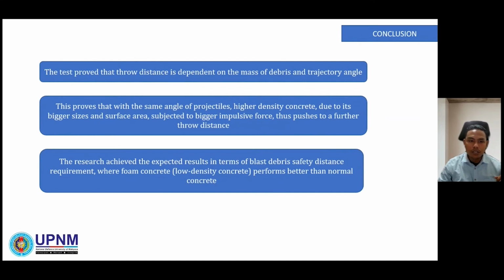To conclude our research, the test proved that throw distance is dependent on the mass of debris and trajectory angle. Bigger size debris is found in 2 groups. One at a closer distance, which is 18 meters to 66 meters to impact point, considered from those in high trajectory, and the other group at far distance, which is 180 meters to 220 meters.